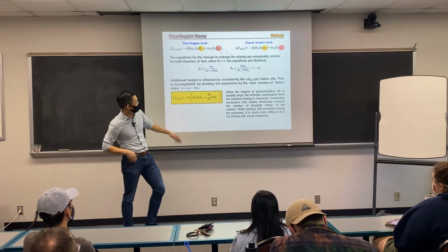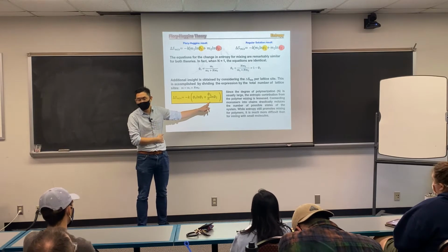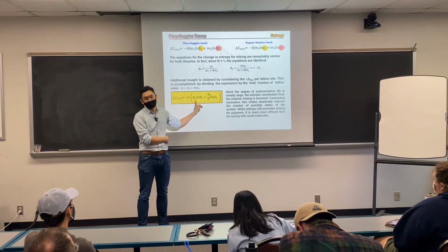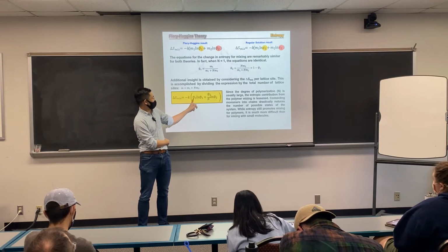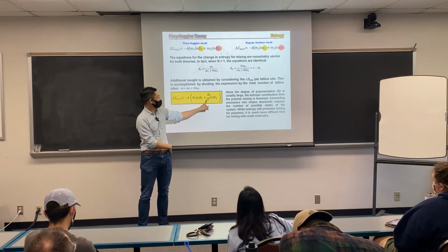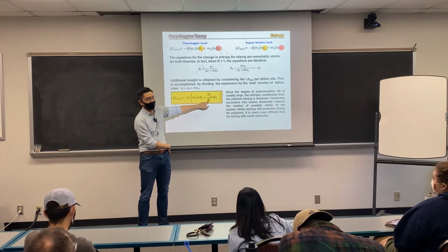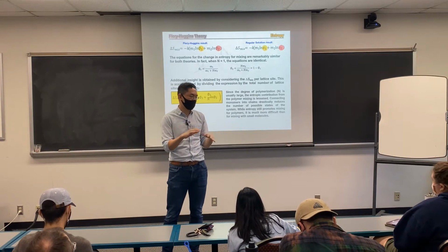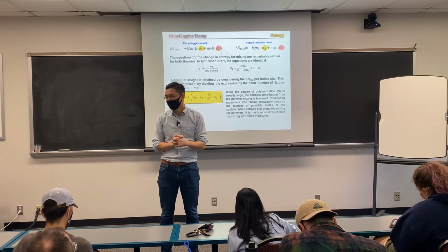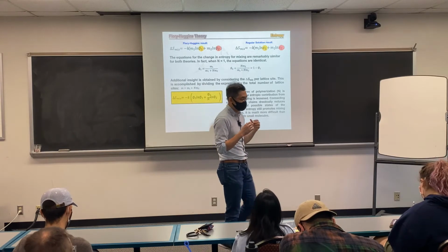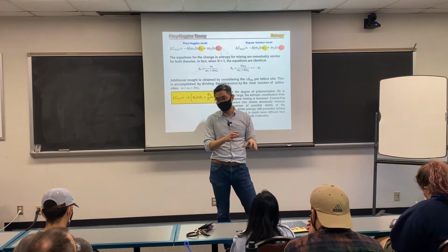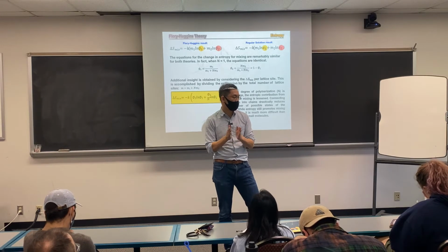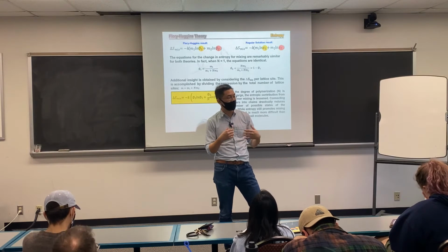So how do we understand? If the degree of polymerization is 1,000, that means the contribution of entropy for this polymer before and after mixing will be much smaller than the solvent contribution, right? If phi 1 and phi 2 are both 0.5, this will be bigger than this by a factor of n. N is easily 1,000. So this means the polymer component doesn't contribute much to mixing. Why? Because think about how much the polymer entropy changes before you mix them. In the solid state, it's already connected. And in the lattice, after it's mixed with solvent, there is just not much change in terms of connectivity, conformation. So your disorder doesn't change a lot for the polymer.